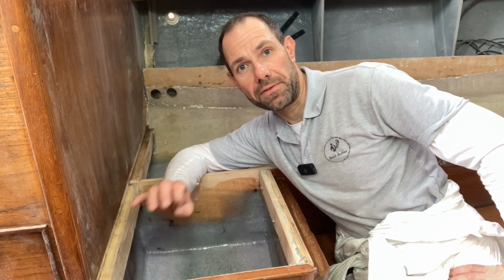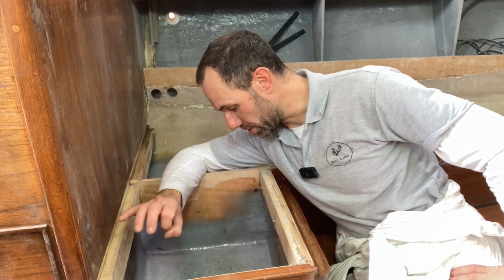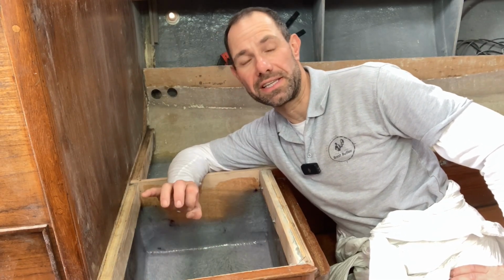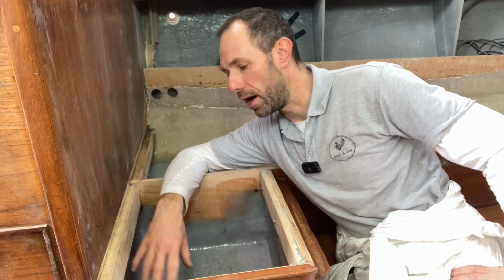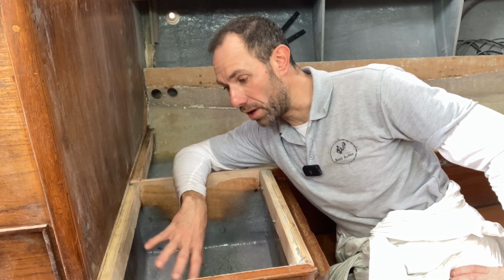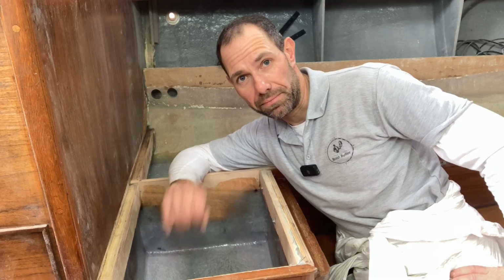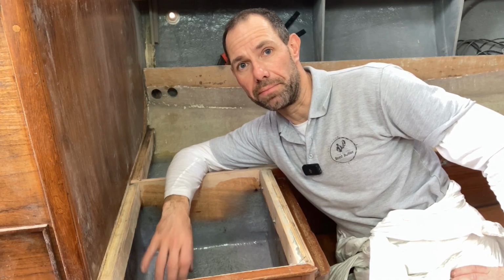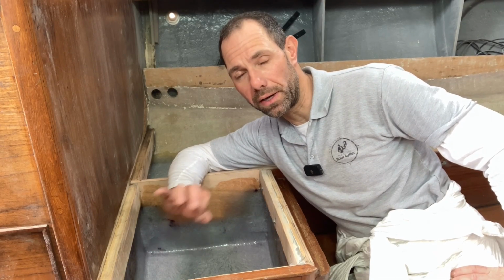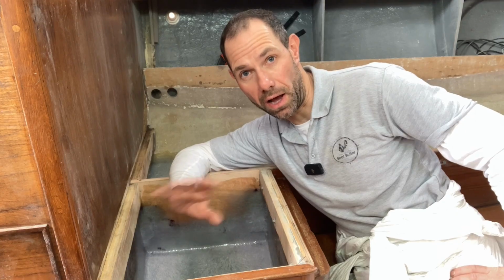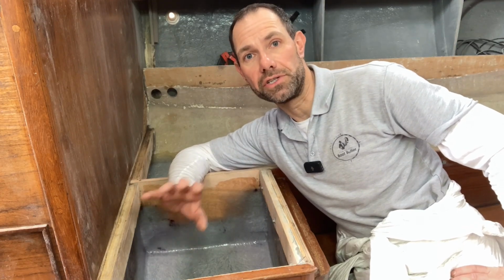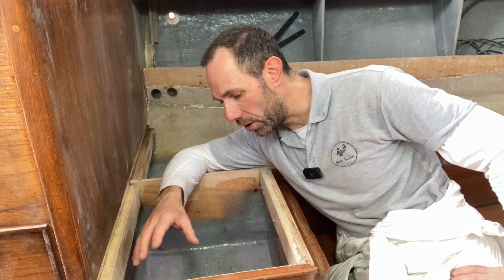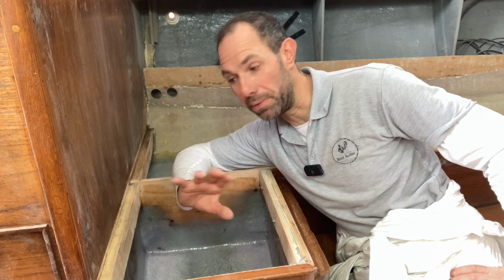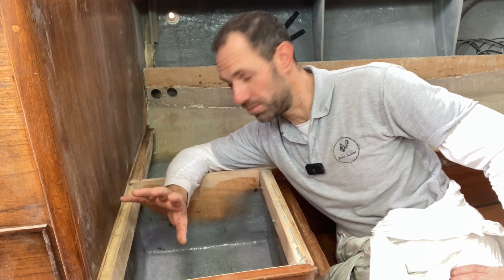Now, as I said, flow coat is a great product for coating the inside of lockers. It's much, much thicker than paint. You can just apply it over wood. You can even apply it over epoxy. I have done it, but the epoxy needs to be 100% completely cured. Otherwise, you will have major issues with it peeling off. It also needs to be well abraded, but it will stick to epoxy. It'll stick to most things, to be fair.